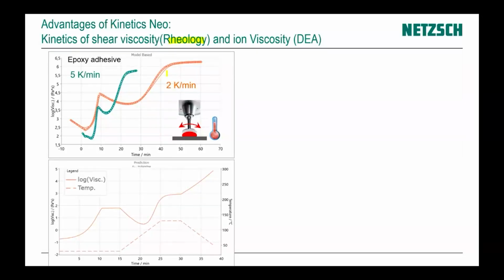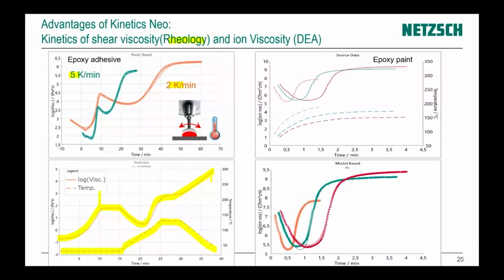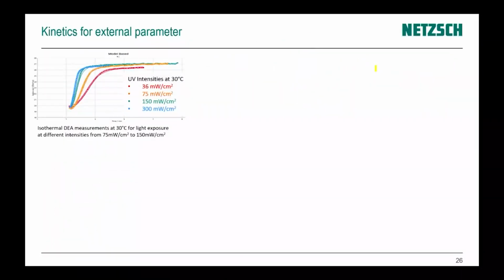Here, rheology, we have data for 2K per minute, for 2K per minute and for 5K per minute. And then after we have a kinetic model, we can make predictions for a given temperature program, for this complex temperature program, and we can calculate the value of shear viscosity, how the shear viscosity behaves during this complex temperature program. We can make the same for ion viscosity measured by dielectric analysis.